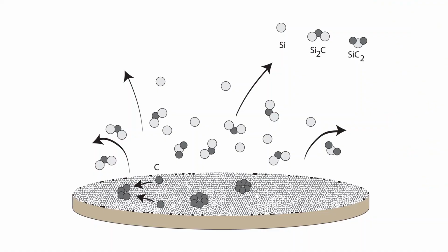So that was an example of how a method came into usefulness in another avenue than the intended one. And another feature with the silicon carbide is that when we heat it up, we have the silicon and carbon. They form species, and if everything goes well, then there's a growth of the silicon carbide, which is nice. But sometimes when we had poor conditions or other things which were influencing, we had more silicon leaving the surface from our material than the carbon.